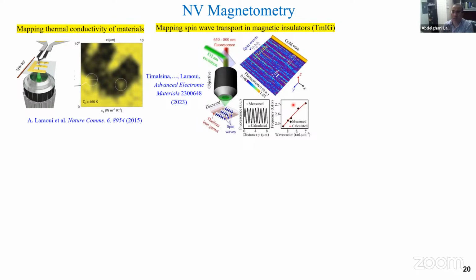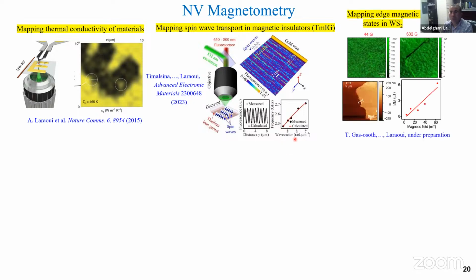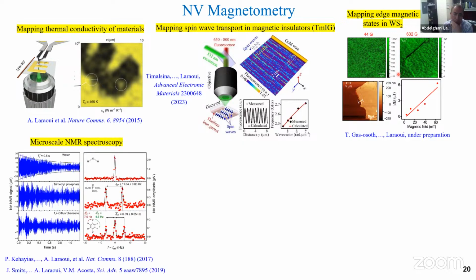In my group as well, you can engineer this diamond, whether in nanocrystals, nanopillars, or thin films. In this case, we have diamond doped with single NVs in contact with a garnet, in this case TmIG. By exciting these spin waves with a gold wire, one can see the interference of these spin waves, and then we can measure, basically, the frequency as a function of the wave vector. Also in my group, we can map edge states from weakly magnetized samples.